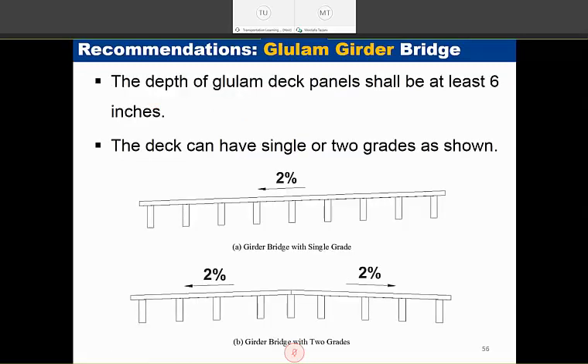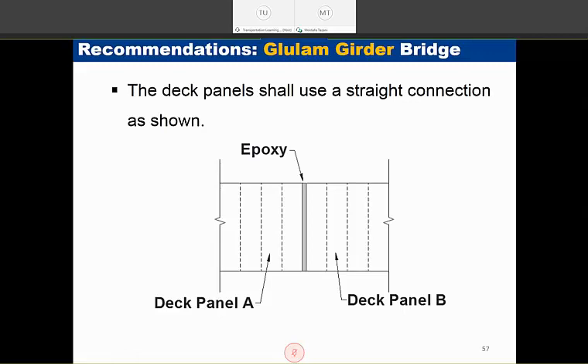The depth of the glue lam deck panel should be at least 6 inches, and the decks can have one grade or two grades, as you can see in these detailings. As I discussed later, the tongue and groove panel-to-panel joints failed under the fatigue testing. So our recommendation is to use flat panel-to-panel joints and fill them with epoxy to make sure that the entire deck is attached and working together and there is no further damage.